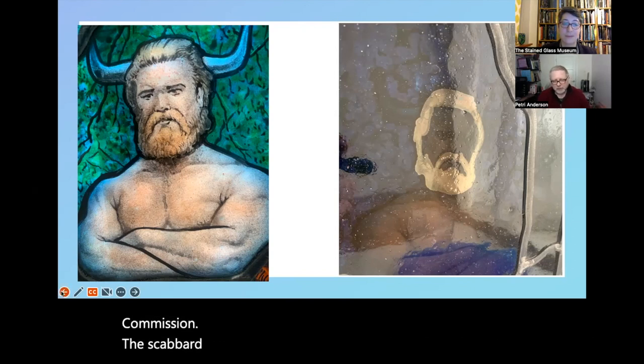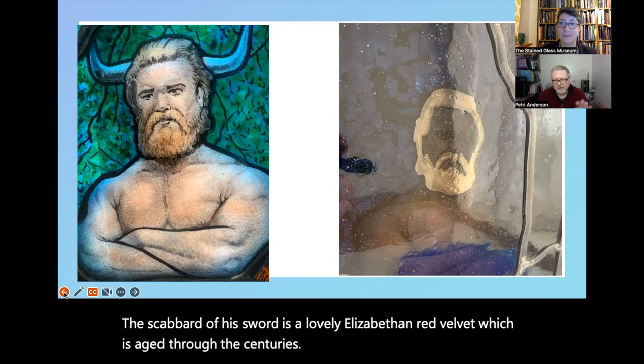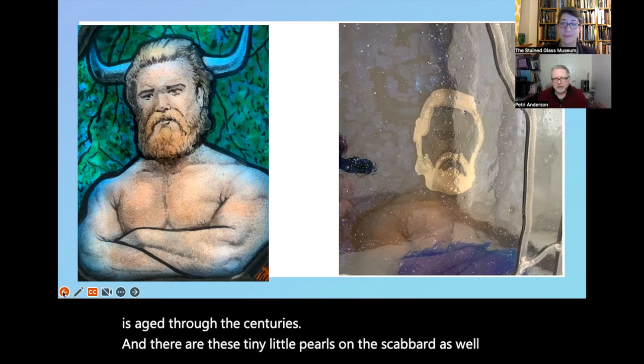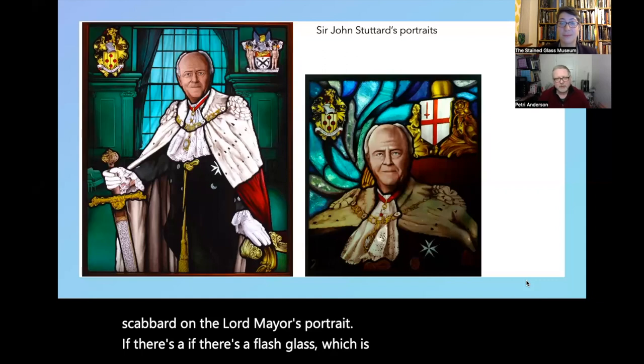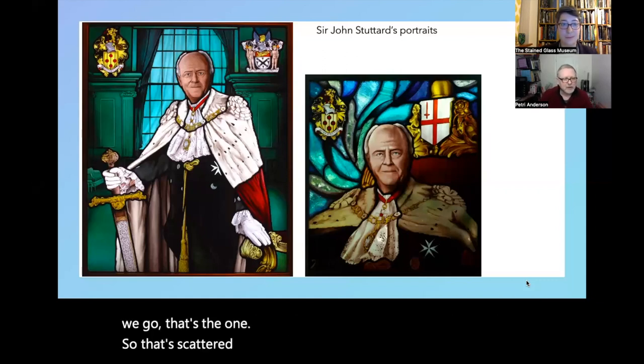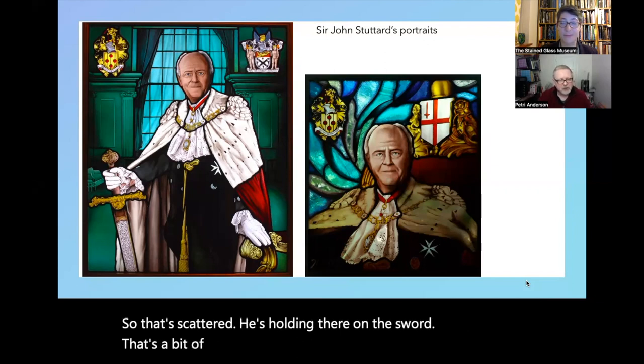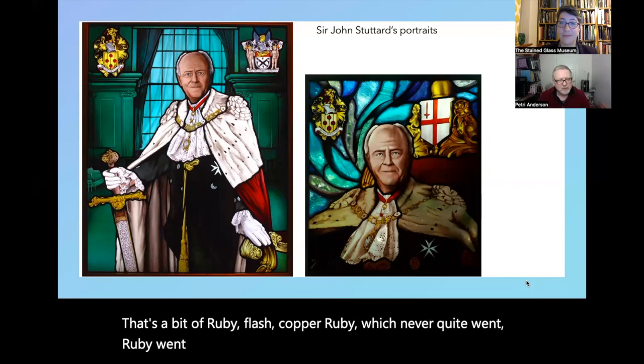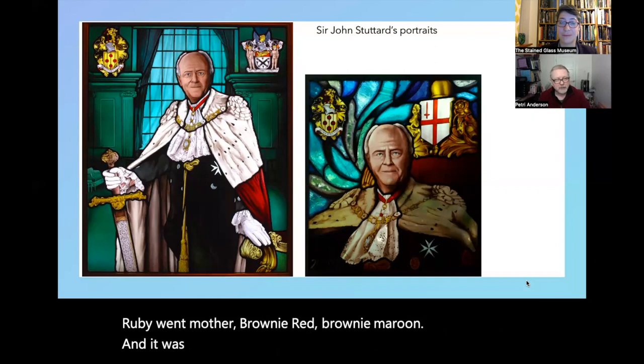the scabbard of his sword is a lovely Elizabethan red velvet, which is aged through the centuries. And there are these tiny little pearls on the scabbard as well. And when I took the photograph at the Mansion House, I knew there was no way I was going to match that colour. And then I went to English Antique Glass, and they would experiment with trying to get some ruby flashes, and they weren't getting the hang of it at all. The glasses they produced were just the right colour for this scabbard on the Lord Mayor's portrait. So if there's a flash glass which is out of the ordinary, there we go, that's the one. So that scabbard that he's holding there on the sword, that's a bit of ruby flash, copper ruby, which never quite went ruby, went more of a brownie red, brownie maroon. And it was just right for that piece.